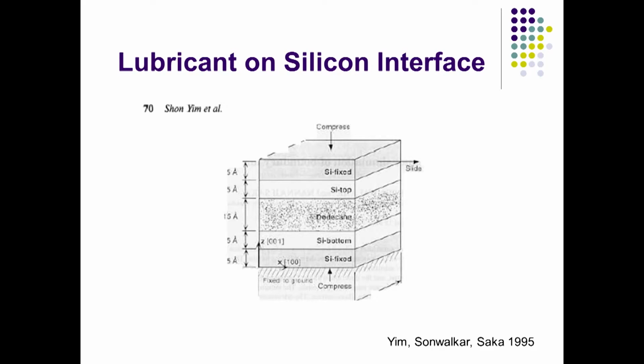So, all of that works here. If I have to ask you a question here, what kind of ensemble will you use? You have to use the isobaric and isothermal ensemble, because you have to relax this particular system and then provide shear between the layers. So, some of the Parrinello-Rahman formulation that you learned earlier is going to be used here.